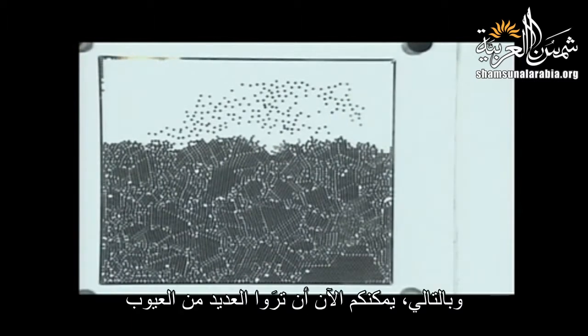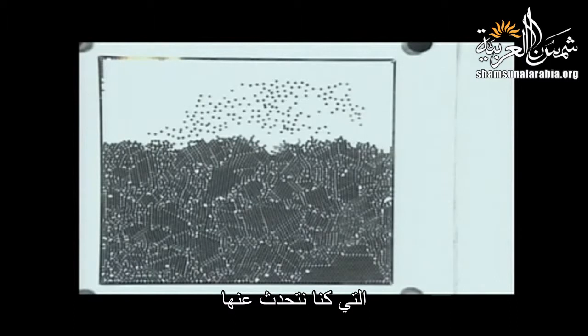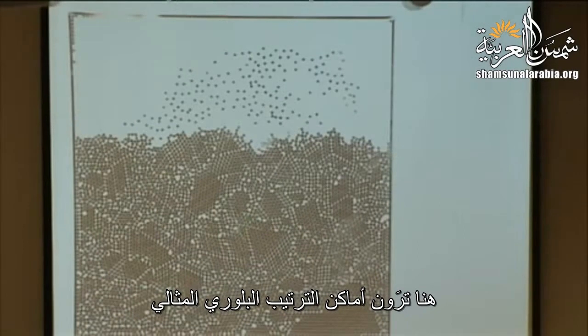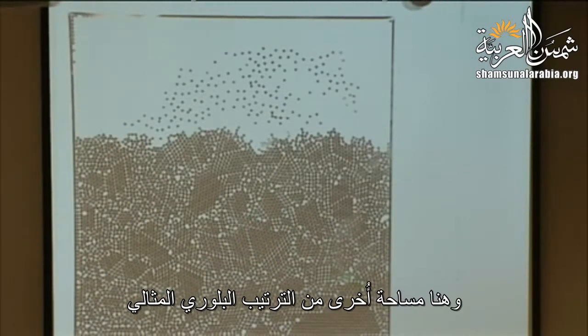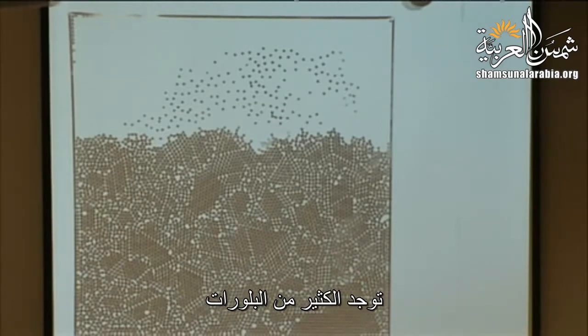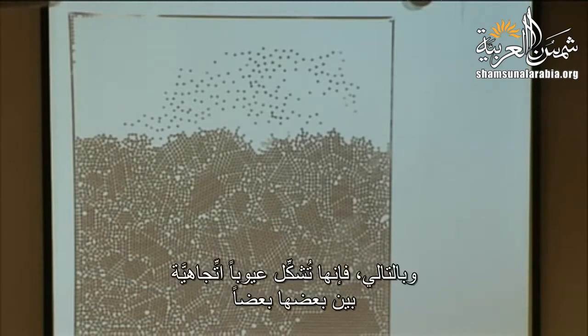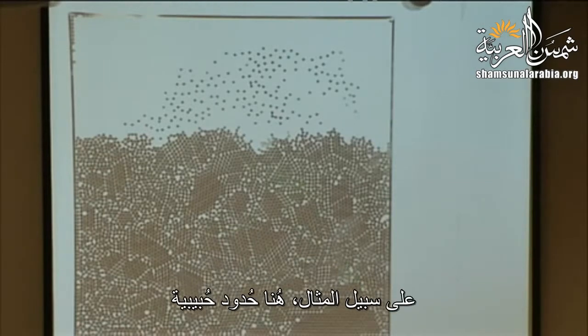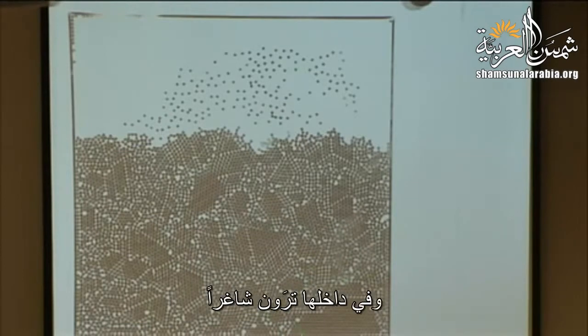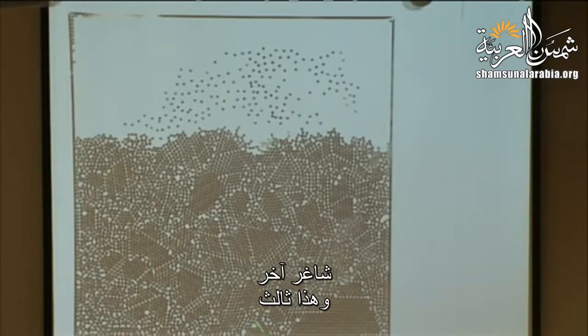So you can actually see a lot of the defects that we were talking about just a moment ago. Here, you can see areas of perfect crystalline order. Here's another area of perfect crystalline order. So you have many, many crystals that are adjacent to each other. They're oriented differently, so they're forming misorientation defects between themselves. For example, here's a grain boundary. This is a crystalline grain. And inside this crystal, you see a vacancy. It's right there. Here's another instance of a vacancy.